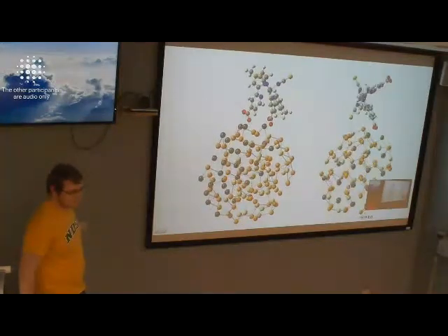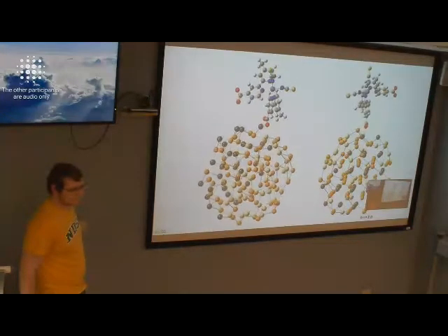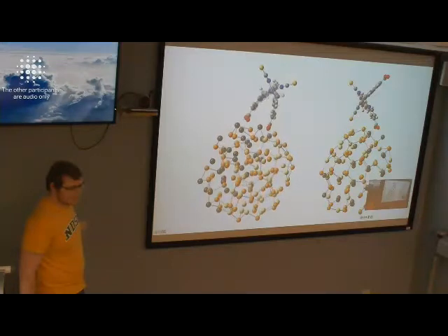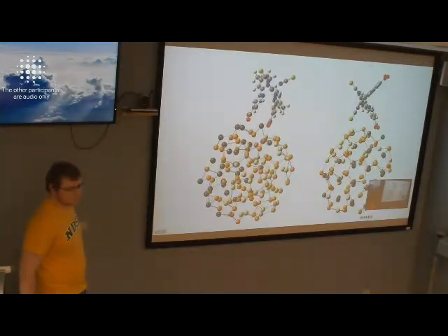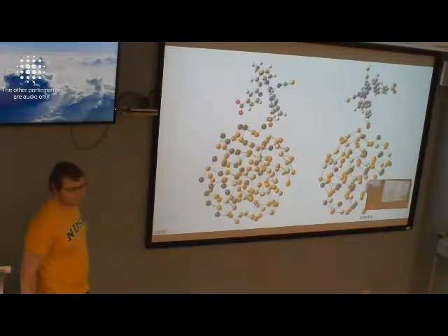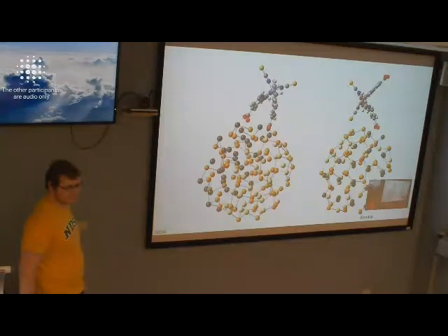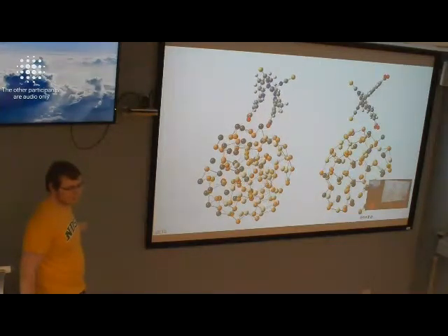So they also have different dipole moments, because they have different metal contributions. But the interface is where you really will have a not even distribution of charges, right? One goes, more negative will go to probably cadmium, and more positive will be much more on the lead side. So this creates a very strong dipole.